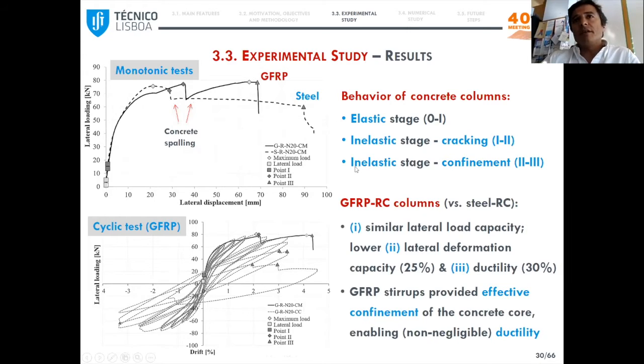So basically, when we compare the GFRP column to the steel reinforced column, we can see that it was possible to obtain a similar lateral load capacity, but however, the lateral deformation capacity and the ductility were reduced by 25 to 30%. So this obviously needs to be taken into account, and we need to do further studies to analyze this reduction in performance. On the other hand, the GFRP stirrups were able to provide relatively effective confinement of the concrete core, enabling